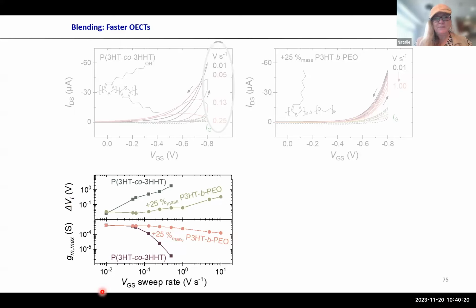And you see the faster you sweep the gate bias, the neat P3HT, versus the copolymer with P3HT, very rapidly over 1 order of magnitude, actually 2 orders of magnitude, you change the threshold voltage. Versus it's pretty stable actually when you add the block copolymer.